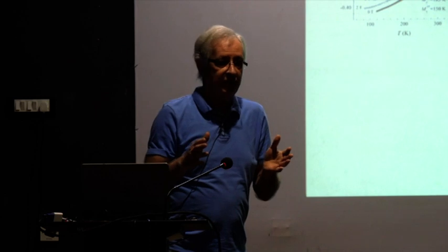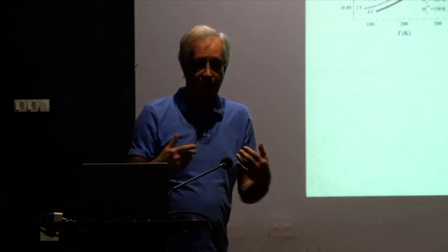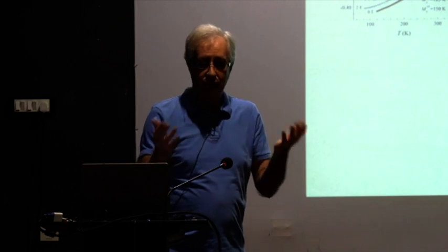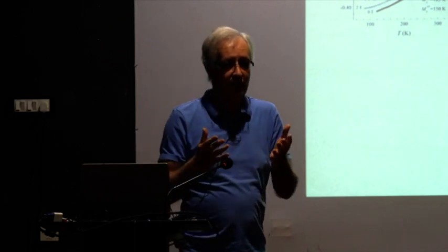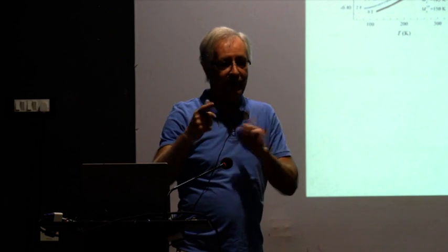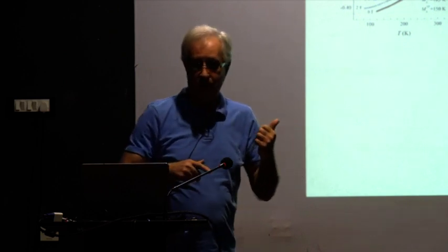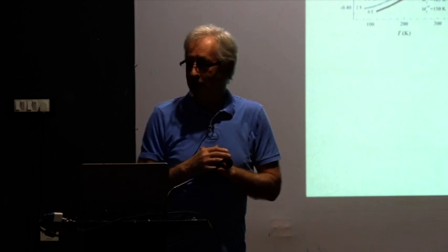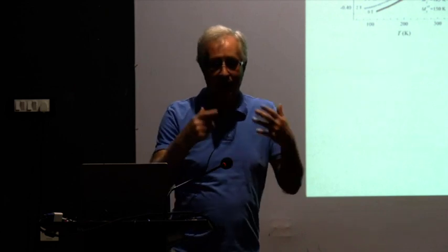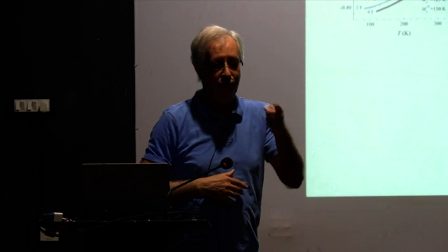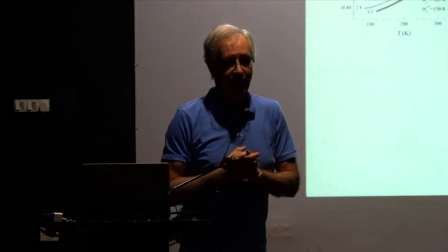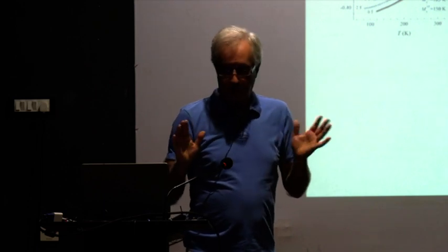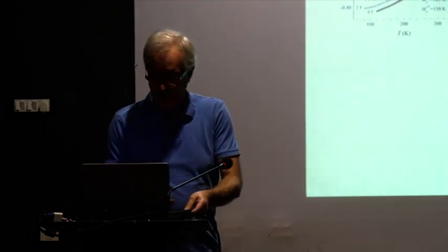And this magnetic property is the magnetic anisotropy. So the easy axis means that you're dealing with the magnetic anisotropy. So the length change under various magnetic fields at phase transitions can give you information on which direction should be the easy axis. These are the kinds of measurements which we can do and play around with.